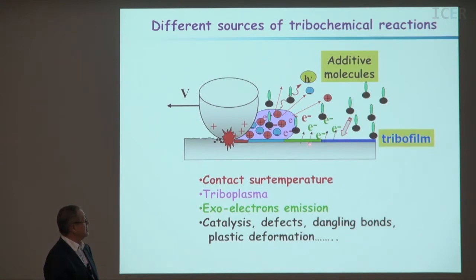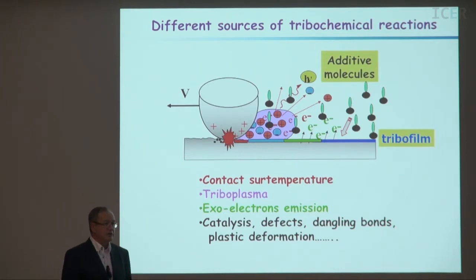And lastly, the surface here is tribostressed, but if it is a metallurgical surface, you can have defects, plasticity, dangling bonds in case of plastic deformation. This also will modify the reaction of the lubricant, which is here, coming to the surface. So typically, this is quite a complex situation.